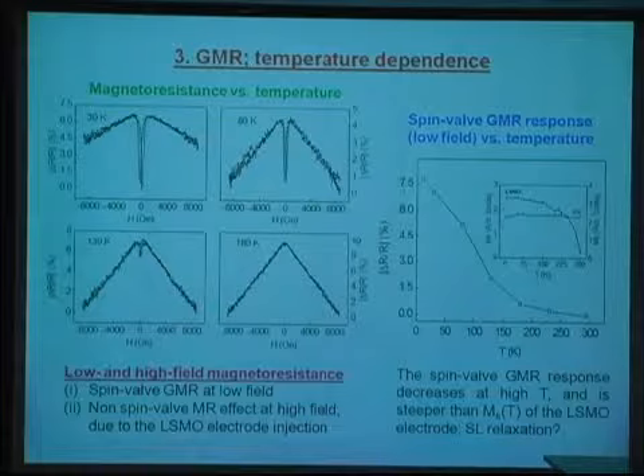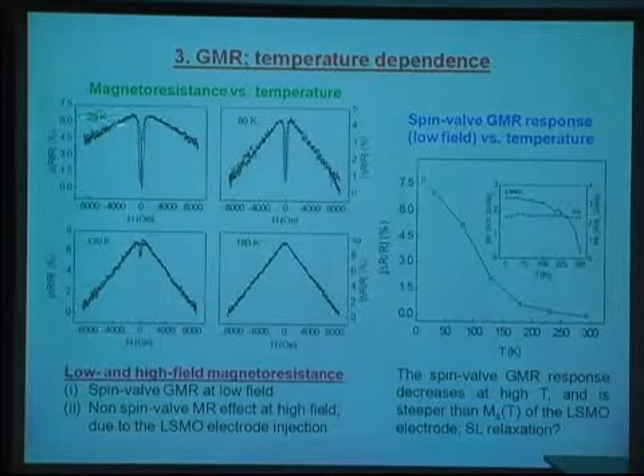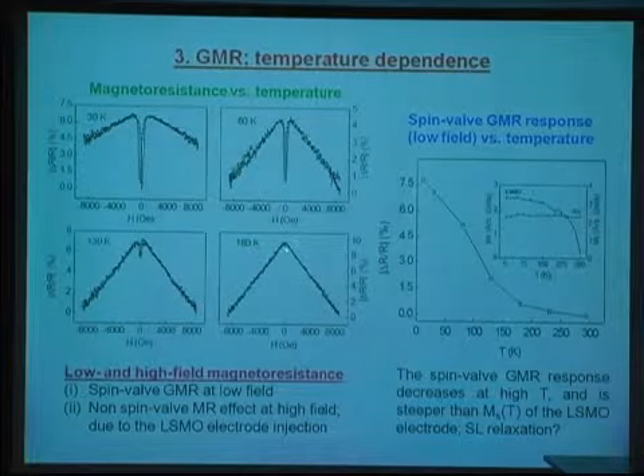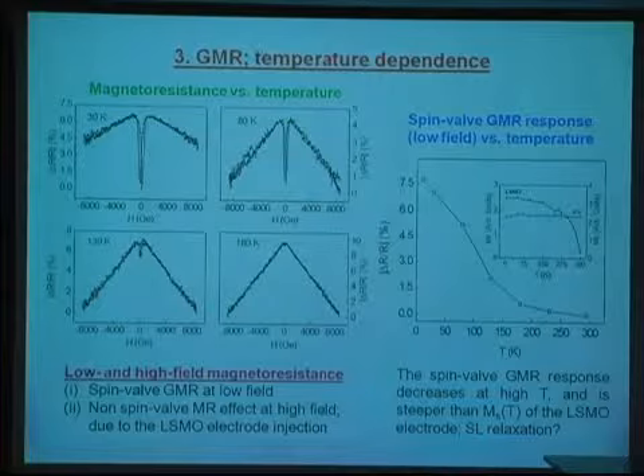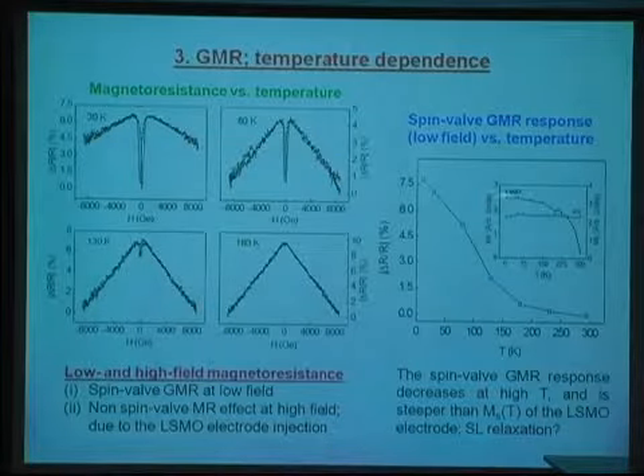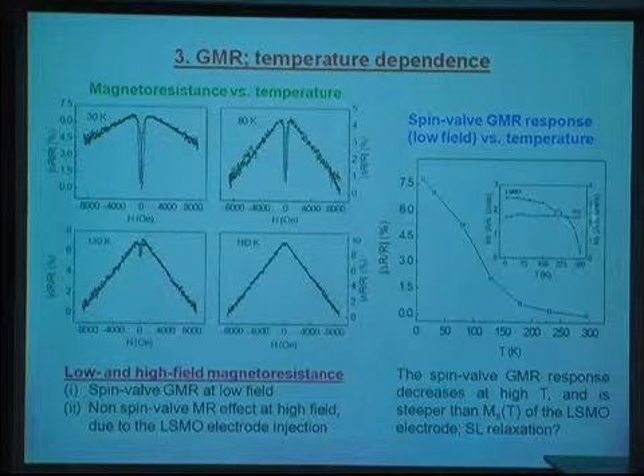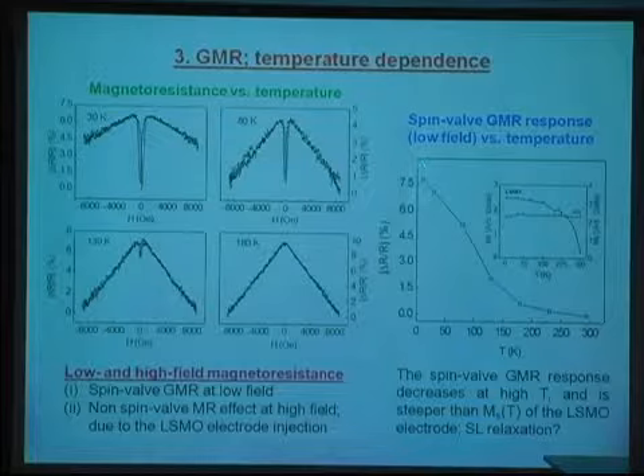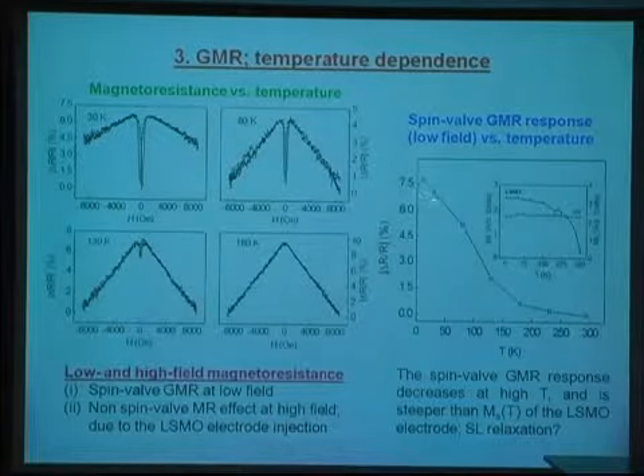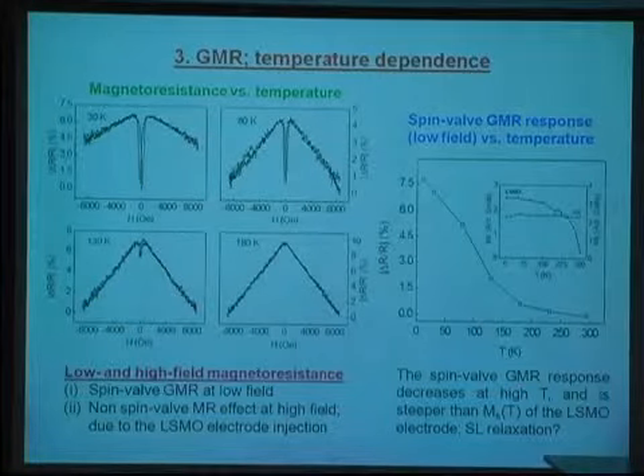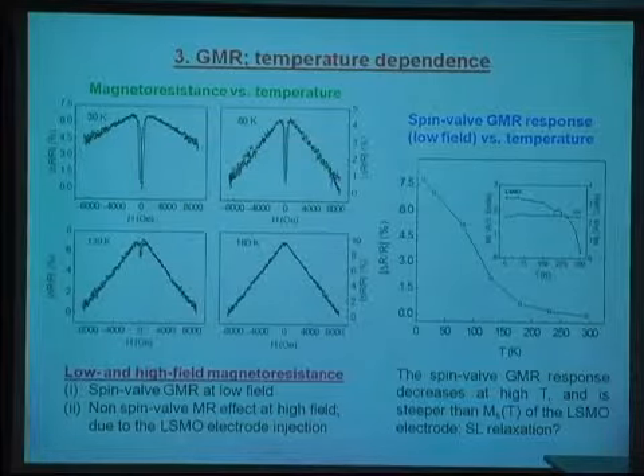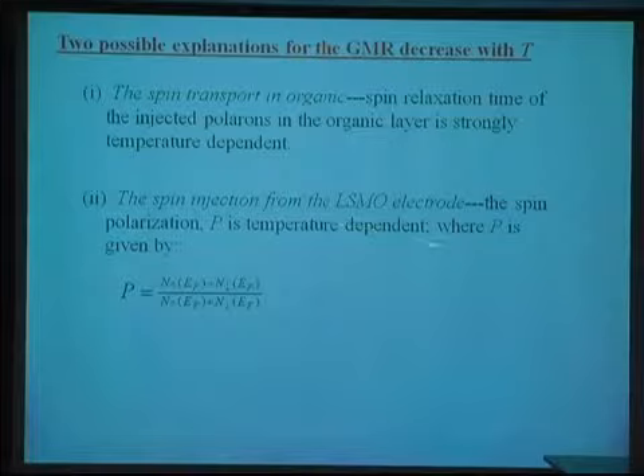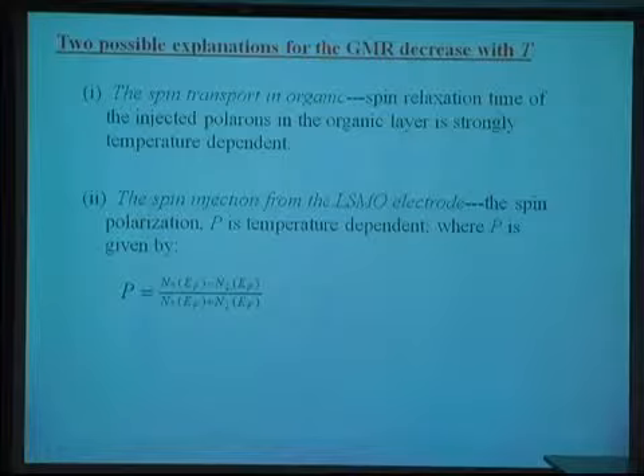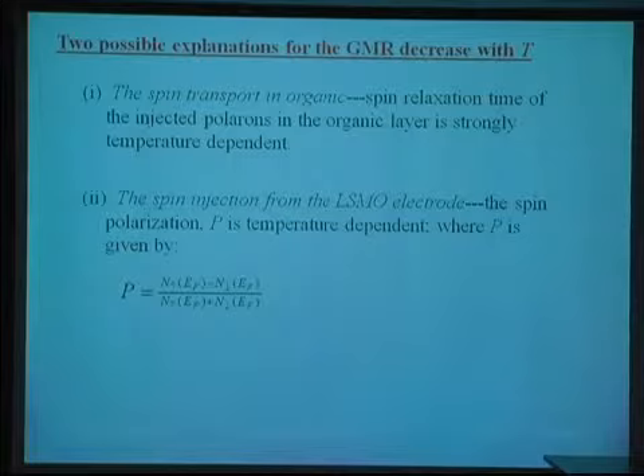Okay, so what is the temperature dependence here? You can see at 30 Kelvin the effect is 6%, but at 180 Kelvin the effect is almost zero. Here is the profile. The magnetoresistance goes down very fast with respect to temperature, and as you can see, the magnetic moment of the LSMO also goes down with temperature. So maybe the small magnetoresistance at high temperature is related to the injection capability of the LSMO. This is one possibility. But the other possibility is that the spin relaxation time of the electrons also has temperature dependence. So which one is more accurate?